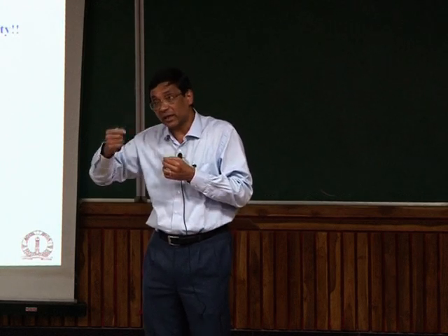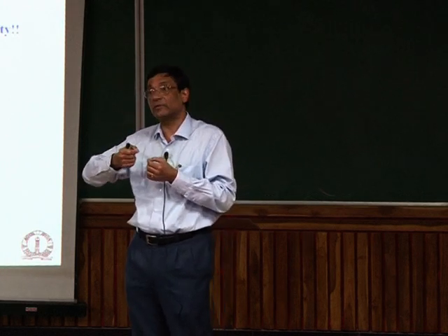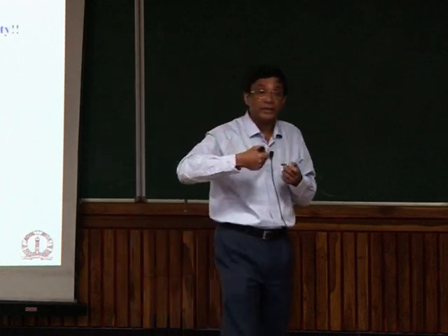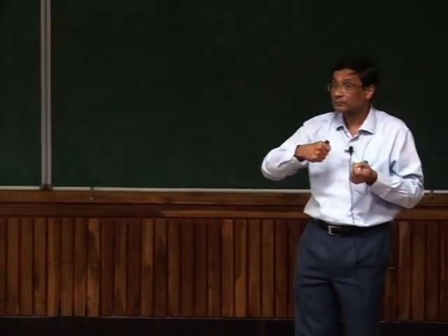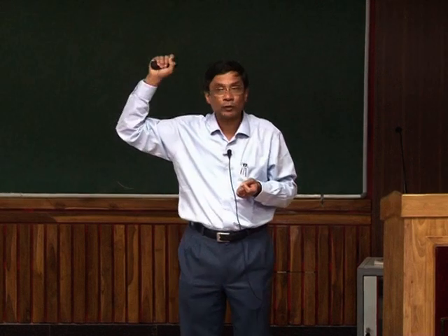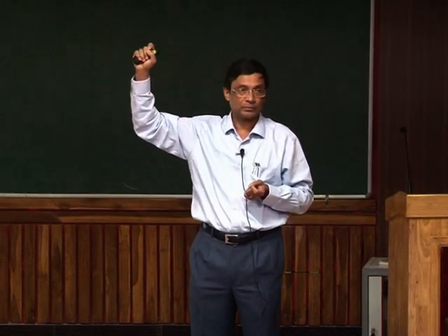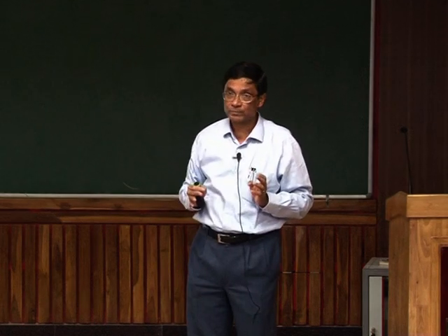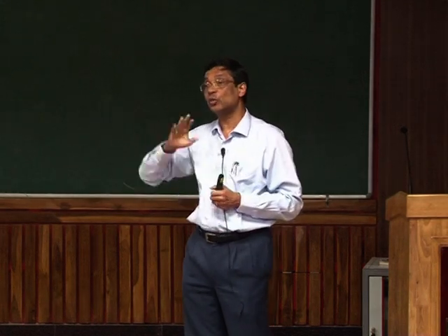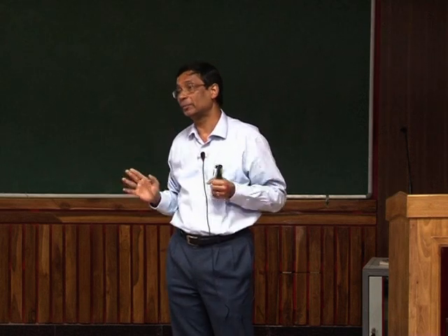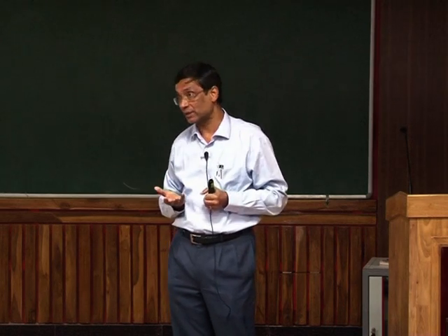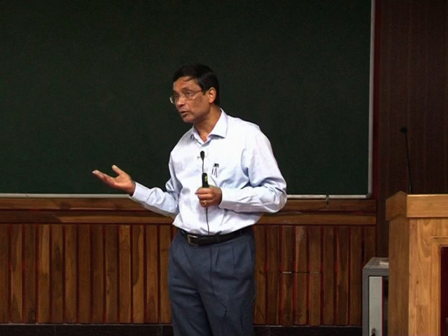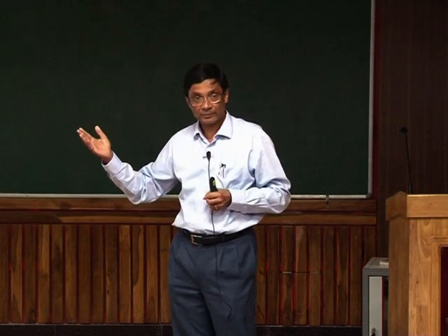Inelastic interaction means an interaction that takes away energy from it, and then I cannot apply the conservation rule. In fact, there is a continuous spectrum of energies that it can lose. Because of this, those electrons are lost from me and they don't contribute to the photoelectric signal. They contribute to the background, which is continuously varying.